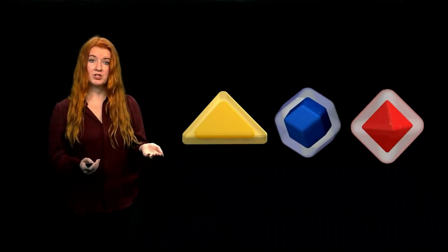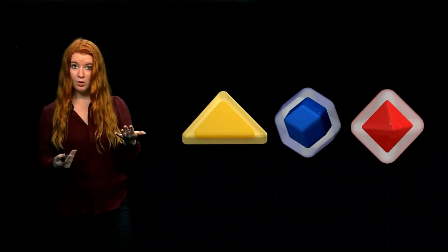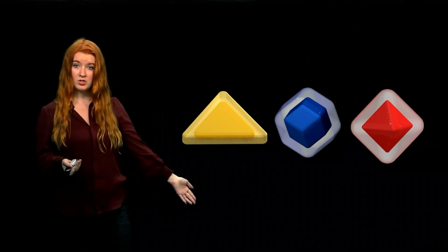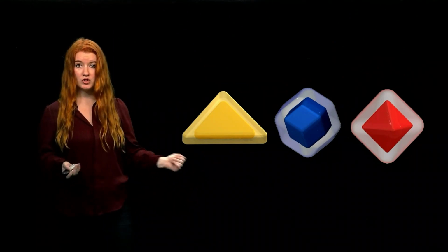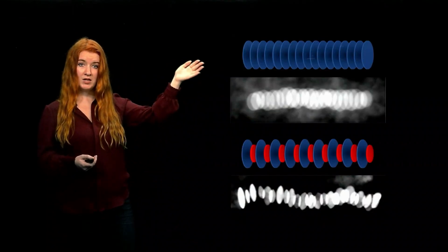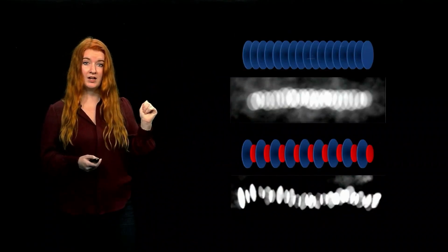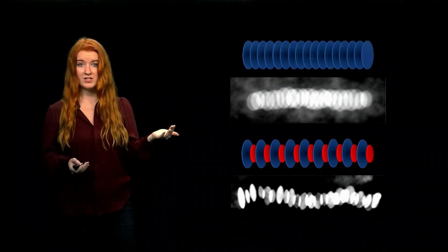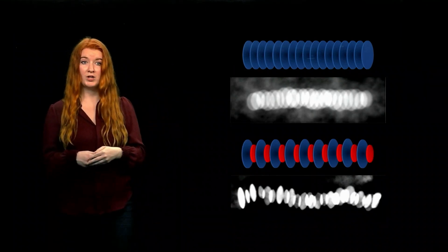The CCM was originally developed in the context of spherical particles, but it can also be used to predict the PAE geometry when particles of different shapes are used. If we use a flat, disc-shaped nanoparticle core, for example, instead of a spherical one, the PAEs can maximize the number of DNA bonds between circular faces by aligning into 1D stacks.